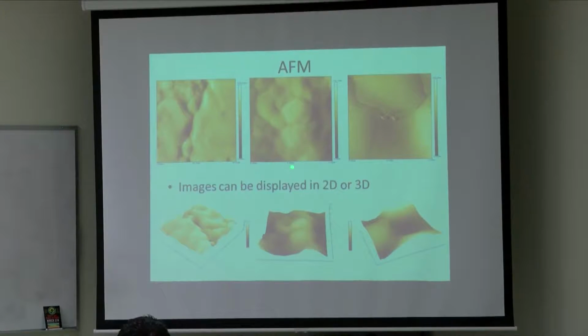The scale of this is a little bit smaller. This is about 10 microns across. So about this big is what you see here. And then this is about 2 microns across. So the atomic force microscope is really nice for taking a really deep look into a sample. So especially if you want to take a look at semiconducting materials, if you're making thin films or anything like that, it's good to see the characteristics of the material itself.